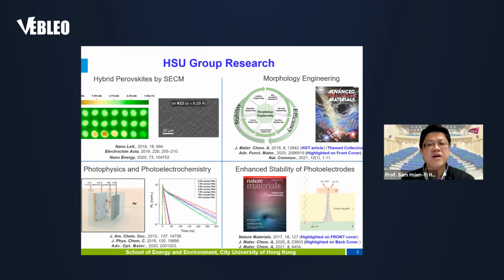It's not conductive. Therefore, in order to prevent the oxidation of the silicon semiconductor, we usually coat an insulator. Sometimes we use aluminum oxide or titanium oxide, and then use a metal catalyst for water splitting. However, if the insulator is too thick, the conductivity is decreased, leading to poor performance. But if the insulator is too thin, the stability is worse.